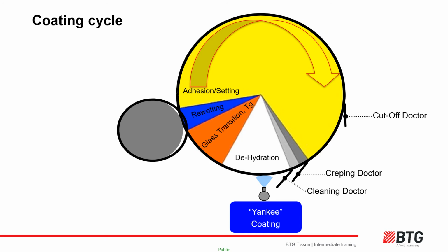It is important to build in a little flexibility at this point as the glass transition phase cannot easily be controlled or even predicted. So the polymers we use must be what we call re-wettable. This means that the moisture from the sheet being presented to the coating reactivates the polymer layer's adhesive nature and accepts the sheet into the coating.